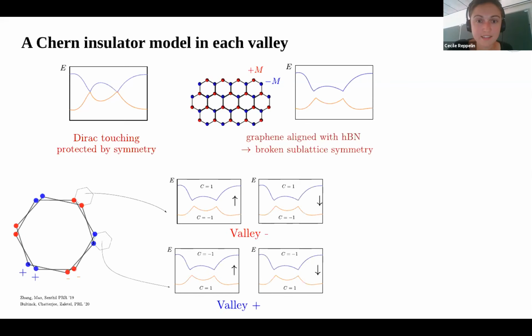All right. So you have now a well-defined Chern number for each of these bands. And because you started from a model where in a given valley, you had the same chirality for each Dirac node, adding this mass will actually create a non-zero Chern number in each of the bands. This is summarized in this picture where if you focus on valley minus, for example, you may have a Chern 1 conduction band and a Chern -1 valence band. That's identical for both spins. And in valley plus, the conduction band, on the other hand, will be -1, and the valence band will be 1, in accordance with the fact that valley minus and valley plus are time reversal partners of one another.